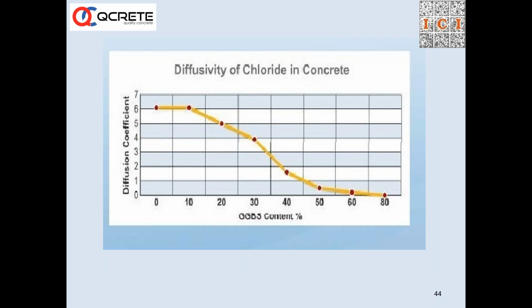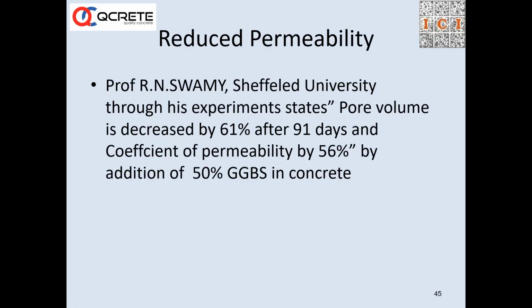Another slide shows the diffusivity of chloride when GGBS usage is increased to between 60 and 80%. You can see the diffusivity is almost nil. Professor R.N. Swamy says there is a tremendous improvement in permeability, and the reduction is almost 56% when 50% GGBS is used. So there is a tremendous possibility of enhancing durability when you are using fly ash or GGBS.